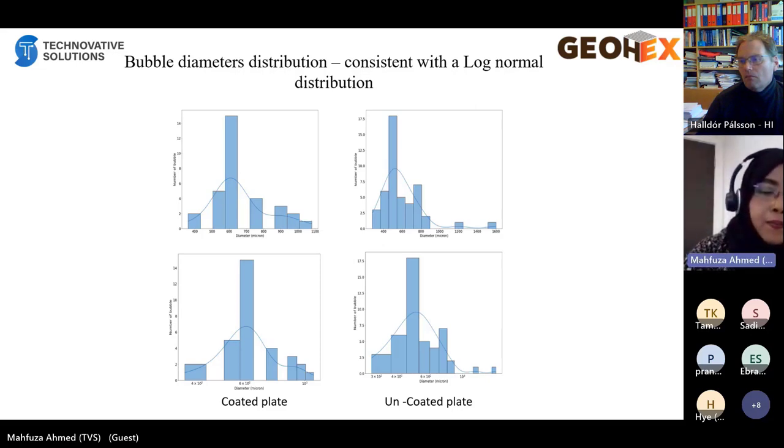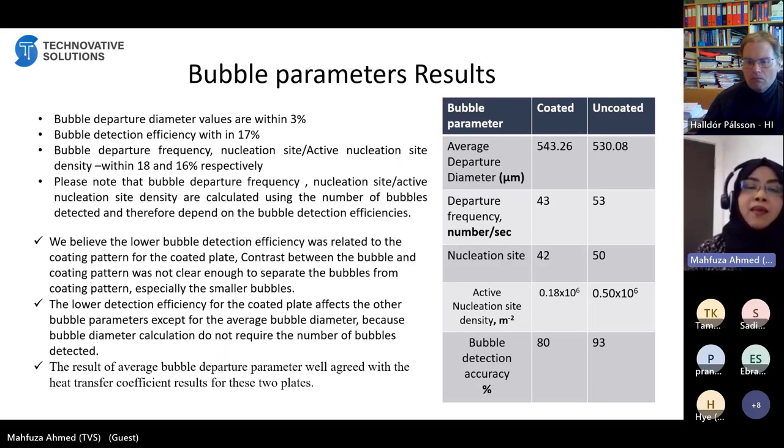So then, coming to the final slide, bubble parameter results. We have calculated the departure diameter, departure frequency, nucleation site, and active nucleation site density. And already Mahmud showed you that we calculated the bubble detection accuracy as well. You see that the bubble departure diameter results are very close for the coated and uncoated plate, within 3%. But the departure frequency is about 18%, and nucleation site and nucleation site density about 16%,